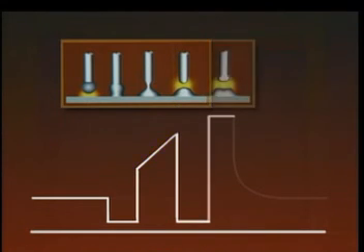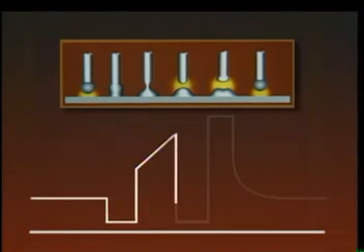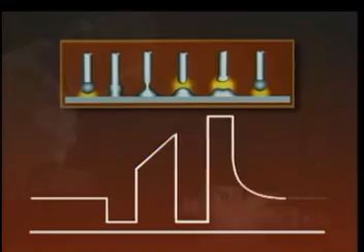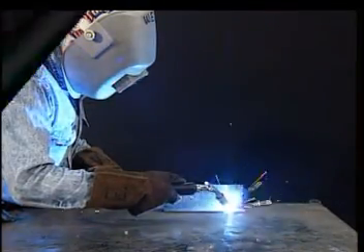It melts the electrode back. This reduces spatter and fume generation. The arc current is then reduced to the background level in a controlled manner, reducing weld puddle agitation. It is the instantaneous control over the current that eliminates the highly violent and explosive energy of short arc MIG welding.